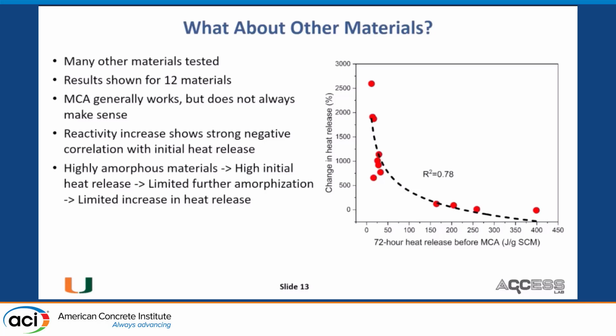So presumably this is because these materials are already highly amorphous to start with. A fly ash or a slag has an amorphous content somewhere from 60 to 90%. You're not going to make the amorphous content 200%, right? So for a slag, we essentially found no real change in reactivity, because presumably what happens is you're not really increasing the specific surface area all that much for these materials, because you are getting the finer fraction, but then you're getting the agglomerates as well.